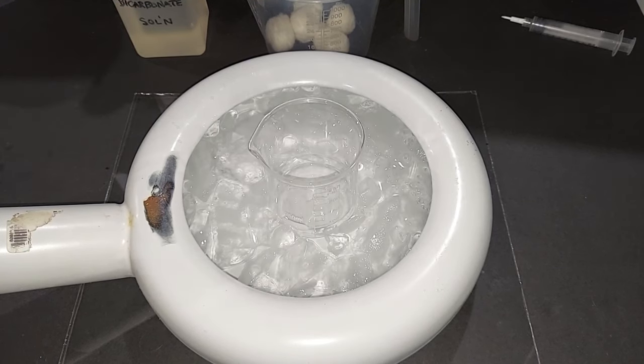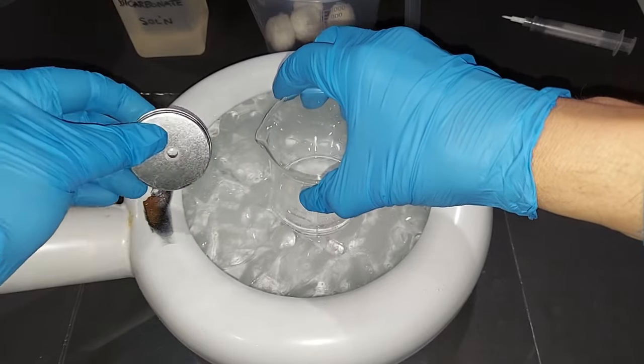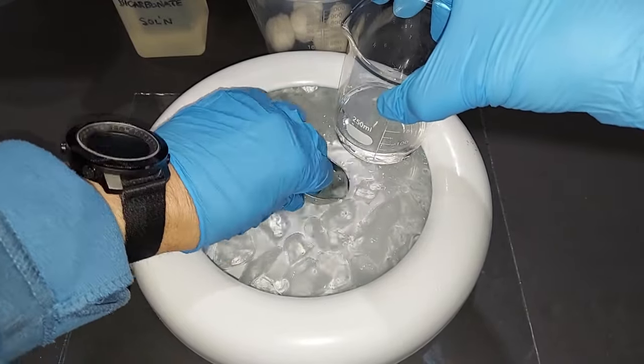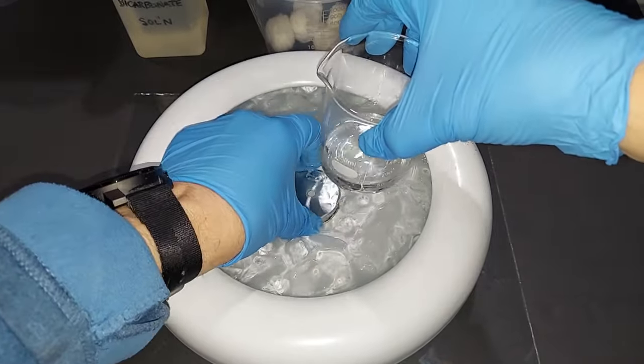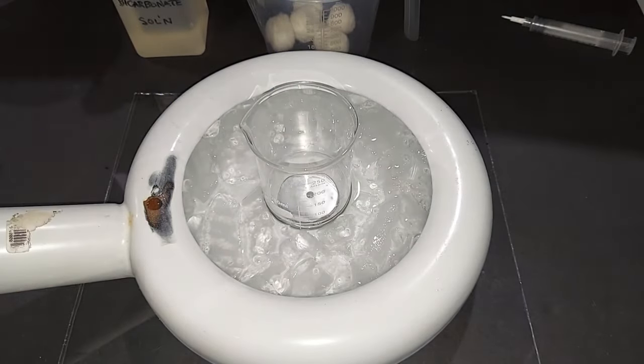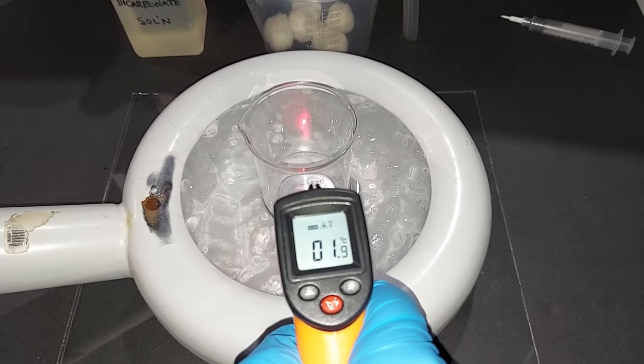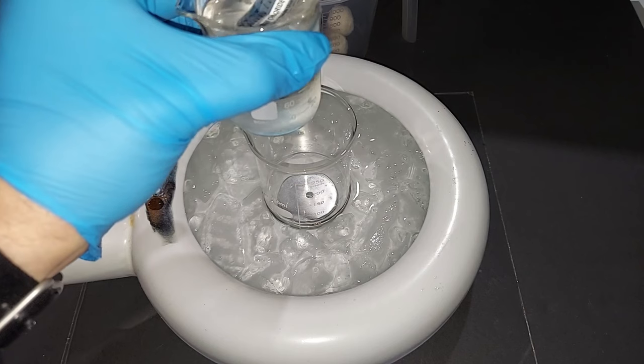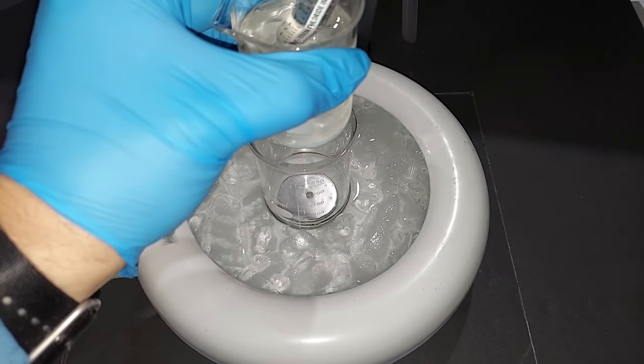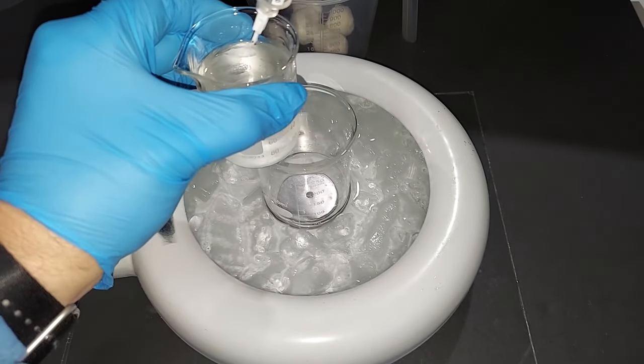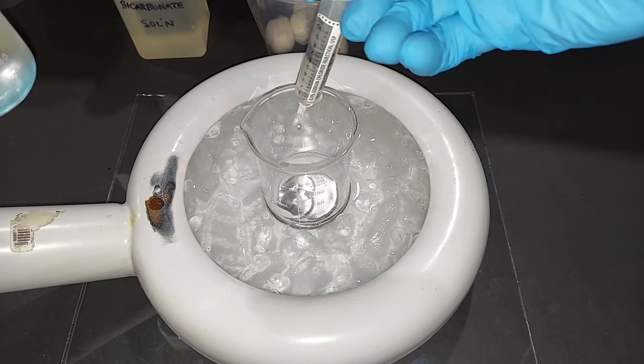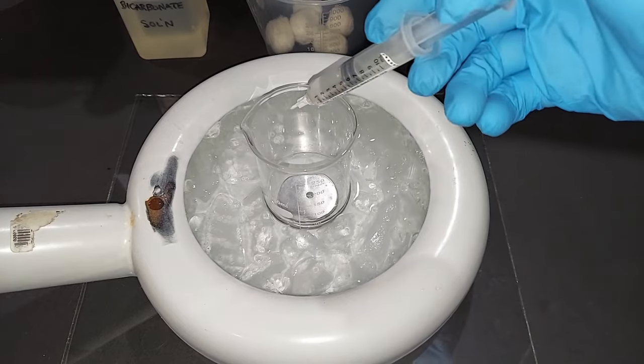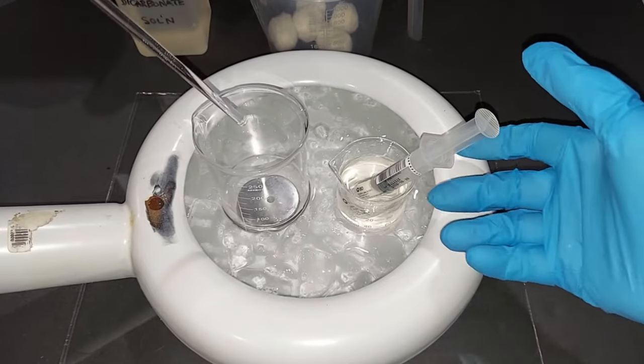I'm going to let that continue to chill for a couple minutes. After a couple minutes, I placed the bottom of the beaker on top of a tin can I drilled a hole in, so everything is suspended in the cold ice water. We're starting with a pretty cold temperature of the nitric acid, around two degrees Celsius. I'm now going to start dripping the sulfuric acid slowly. As we add the sulfuric acid, as long as we keep the temperature down low, we shouldn't have any nitrogen dioxide form. I'll be pulling it up inside the syringe and drop by drop adding it, waiting a couple minutes between additions.